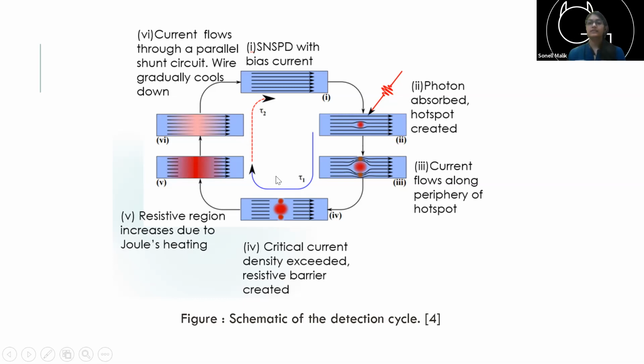Even for a nanowire of width, say, 100 to 200 nanometers, we would expect the resistance to be around 200 ohms if the whole width becomes normal, ceasing to be superconducting. So in parallel to our SNSPD, we keep a 50 ohm resistor where all of the current will be redirected. Now the resistive region here increases because of Joule heating, and the current starts flowing through that shunt circuit, which has a smaller resistance than our SNSPD. And because the current has been redirected, there is now no current passing through our SNSPD, which allows it time to cool down.